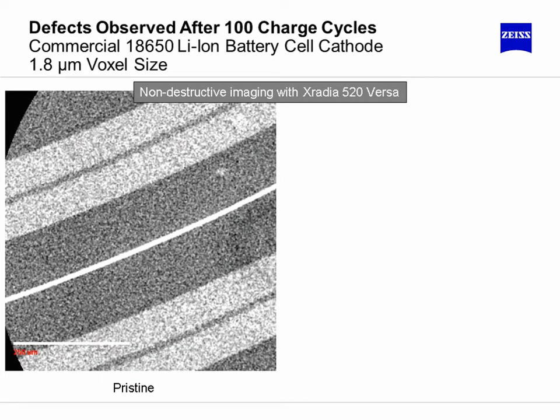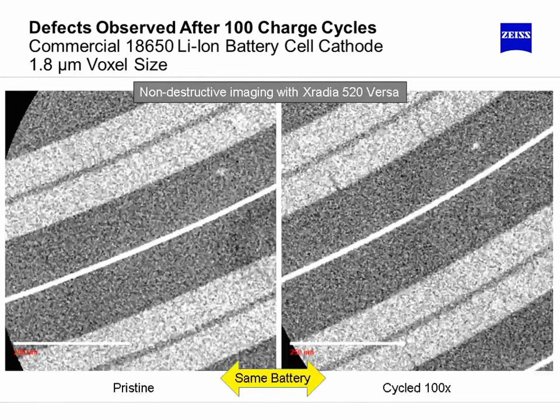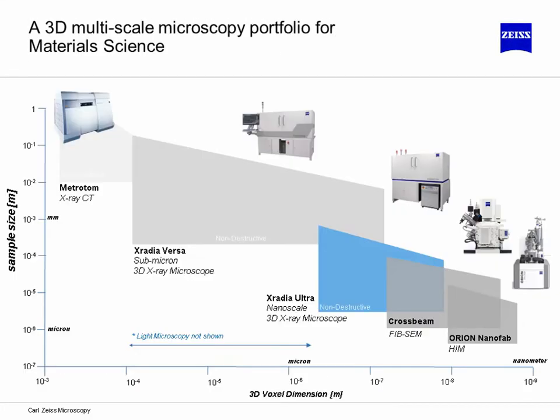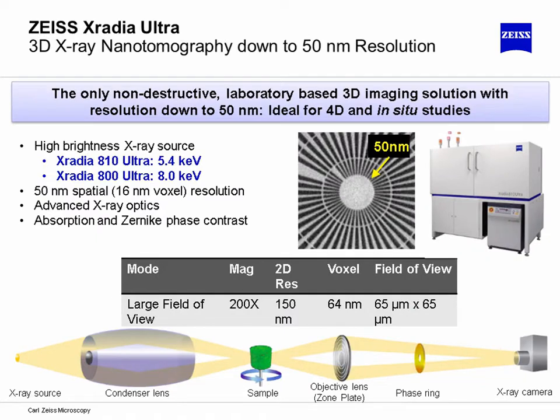And you can even image, this is an 18650 cell that was imaged, and an interior tomography was taken here on the left-hand side. And after several electrochemical cycles, cracks were witnessed on the right-hand side at specific locations. And this can be quantified as depicted here in the green circles. So to look at this evolution information completely in an embedded, non-destructive way is quite a powerful technique.